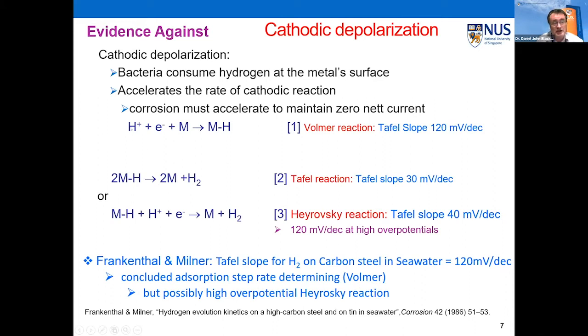They concluded from that that it's the adsorption step that is rate determining. If this was the rate determining step, it wouldn't really matter if you removed hydrogen, because you're only going to be accelerating reactions 2 and 3. So under that, the cathodic depolarization can't be true. However, there's a slight snag: I've started realizing that the Heyrovsky reaction can also give 120 millivolts per decade if you have high overpotentials.